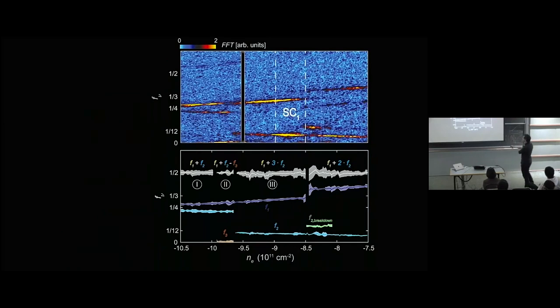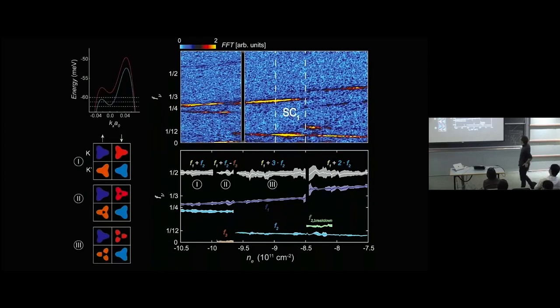Okay, so you have different Fermi surfaces than you did before, but they're consistent with the single particle picture once you put in this 1.5 meV of spin-orbit coupling, which doesn't sound like a lot, but it's a lot. The Fermi energy is maybe only a few times that. So it's a spin-orbit coupling that's almost as big as E Fermi, right? And certainly it's comparable or bigger than most of the interaction energy scales. Okay, so SC1 is another one that looks pretty standard.